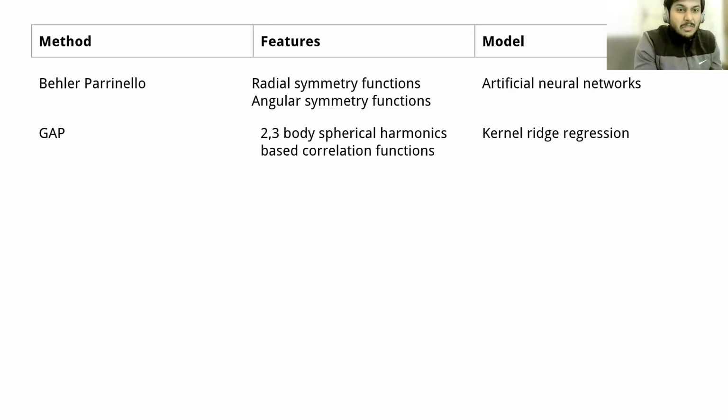Or a Gaussian, basically. So it encodes the radial term. And as soon as you include the L equals 1 term, it also encodes some dimension, some directionality. Now you can represent your total density as a sphere plus some additional perturbations along directions, in fact, along any direction. And then if you take L equals 2, you can also encode two body terms in this case.